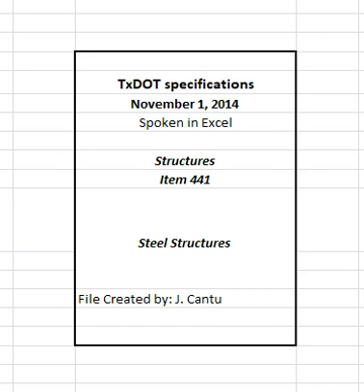3.2.1.3 Weld termination. Terminate fillet welds approximately 1/4 inches from the end of the attachment except for galvanized structures and flange to web welds, for which the fillet weld must run the full length of the attachment, unless otherwise shown on the plans. 3.2.1.4 No paint areas at field welded connections. Keep surfaces within 4 inches of groove welds or within 2 inches of fillet welds free from shop paint. 3.2.1.5 Galvanized assemblies. Completely seal all edges of tightly contacting surfaces by welding before galvanizing.